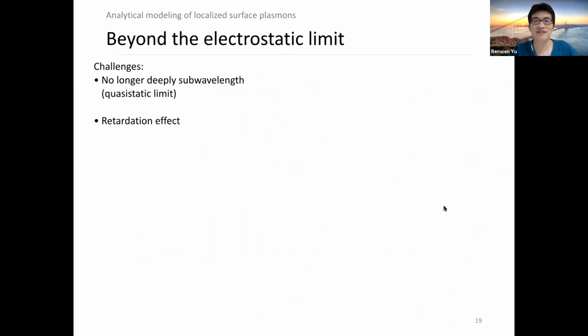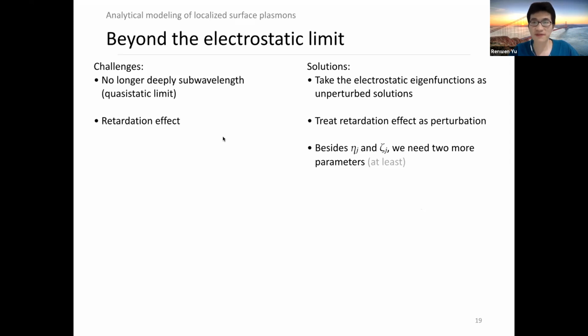However, this is just part of the story, because if we consider noble metal-based nanostructures, they are not as subwavelength as graphene-based nanostructures. So we are not in the electrostatic limit. We are in the so-called quasi-static limit, and the retardation effect needs to be taken into account. To solve this problem, we can take the electrostatic eigenfunctions as unperturbed solutions and treat retardation effects as perturbation. Then we can add some correction parameters to these two unperturbed parameters to get the correct optical response.